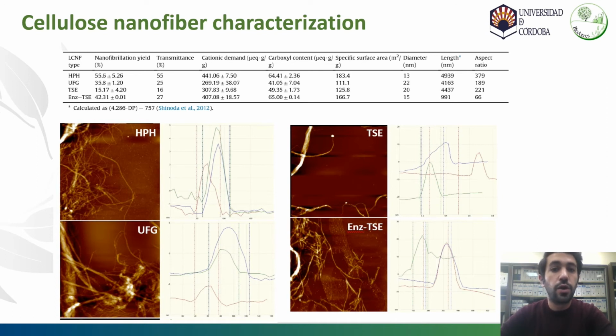It is observed that all of them present similar length, but if we observe the aspect ratio, that is the length-diameter ratio, we see how those obtained by homogenization present a higher value. This value is closely related to the reinforcing effect that nanocellulose can exert as reinforcement in material, so it is a parameter of special interest.